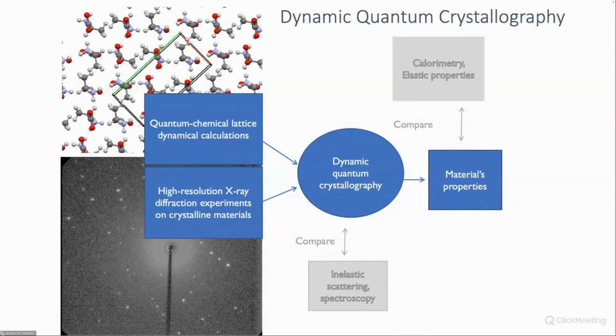So with that tool in hand, this way of calculating the displacement parameters, we can now combine elastic diffraction or standard X-ray crystallography measurements with these lattice dynamical calculations. So we take some high-resolution X-ray diffraction experiments, we take these lattice dynamical calculations, and we combine them into what I have coined dynamic quantum crystallography. And from that, we can derive some information about the frequencies of these lattice vibrations, and hopefully we can use that to compute some materials properties and compare, for example, with other types of experiments of that type.